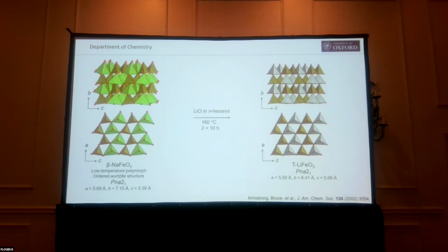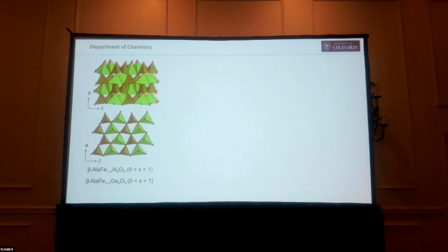What you can do is take a sodium form, beta NaFeO2, which has an ordered wurtzite structure. So hexagonal close packing of the oxide layers, and then we fill half the tetrahedral sites with iron and sodium in ordered stripes. And what you can do is replace the sodium with lithium to make what's called tetrahedral LiFeO2. So what we plan to do is then substitute some of the iron with more gallium, an attempt to stabilize this framework so we don't get the migration and we don't get this redox.